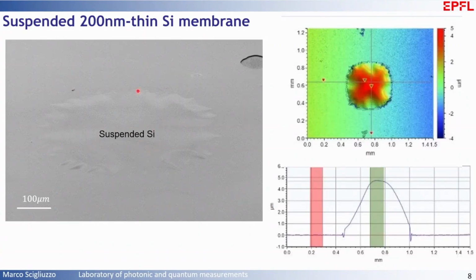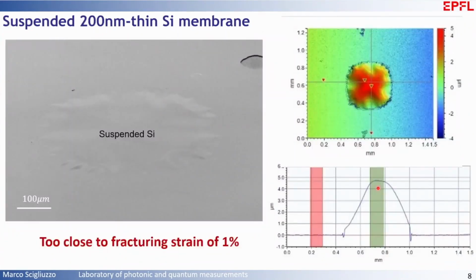Now, since you can see it on the SEM, it means that there is some topography. Indeed, if you now use some profilometer, you can see that you get, every 500 micrometers, a 5 micron buckling up. This means that it's indeed close to the fracturing point, but that's the maximum you can suspend.